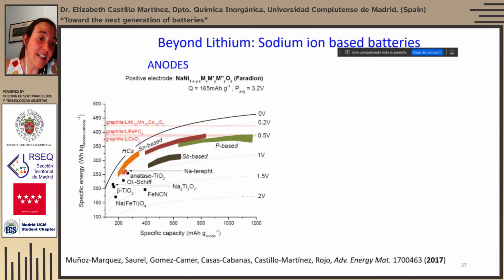These materials actually have relatively good performance, although if we look at this plot of specific energy, considering the weight of the anode and cathode material, for a positive electrode composed of a layered sodium oxide by the British company Faradion, taking into account the specific capacity of each anode material and the voltage at which the reaction takes place, which is indicated by these dashed lines, we can see the specific energy of the system. And we can see that actually sodium-ion batteries do have a slightly lower energy and specific energy than lithium-ion batteries, but they have other advantages, such